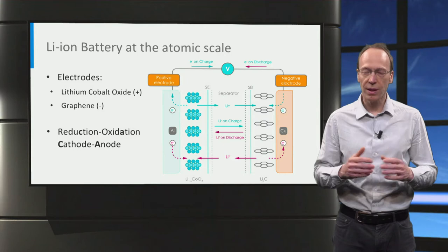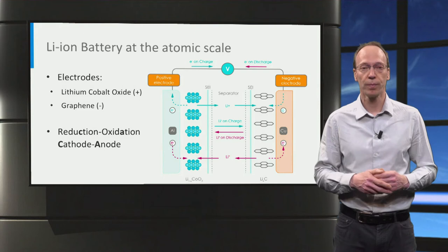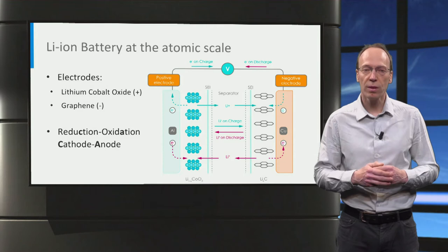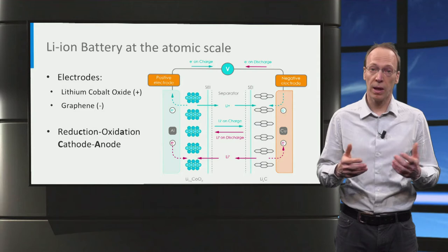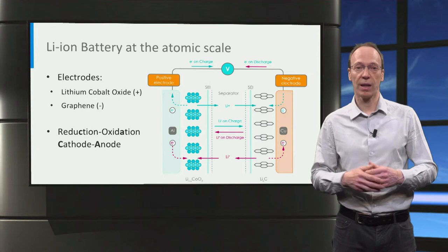but only if the lithium ions are allowed to move through the electrolyte from the negative to the positive electrode. The electrolyte only allows passage of lithium ions — positively charged lithium. Therefore, discharging requires the electrons to go through the external circuit. Only when the external circuit is closed via an application will an electrical current run, driven by the lithium ions that migrate from the negative to the positive electrode. Under these conditions the battery is discharging.